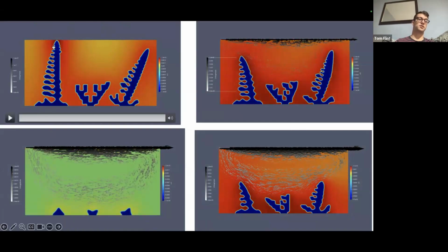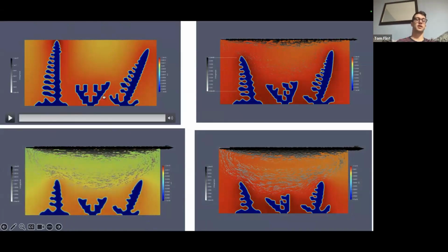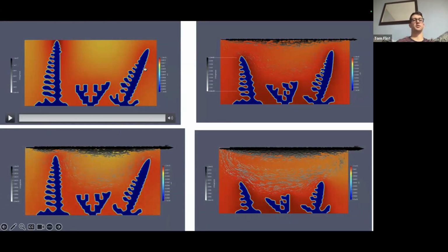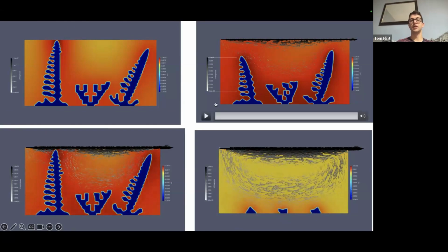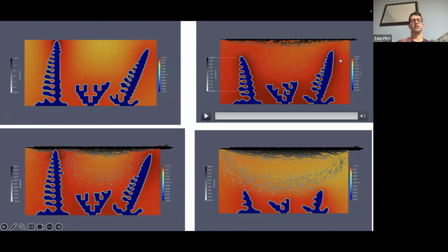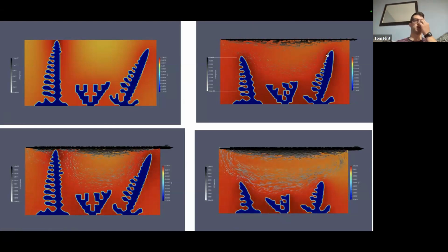So the crystal that's preferentially aligned with the domain grows, obviously, preferentially. This one in the middle is rotated 90 degrees, and this one's rotated like 45 degrees. This one's rotated 22.5 degrees. And actually what you see is that when you apply different velocity fields, and it's all very complicated because you get solute redistribution, there are two competing things going on, depending on the temperature. Sometimes the dendrites grow into the flow field, sometimes they grow away if they're driven more by solute redistribution.